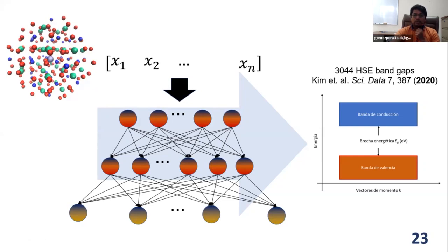And we used the values reported by Kim and co-workers in 2020, which are band gaps calculated with a hybrid functional, the HSE functional, which is supposed to be better than PBE or generalized gradient approximation functionals. This work has not been published, but we obtained a mean absolute error of 0.55 electron volts with compounds of the training set, that is during optimization. And in the test set, we obtained a mean absolute error of 0.72 electron volts.